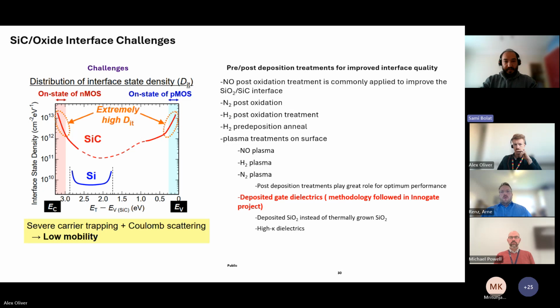If we go to the next slide, I will briefly mention why it is this much worse compared to silicon. So here we see the interface state density distribution across the band gap of our semiconductors. For silicon, we see that the levels are in the order of 10 to the 10. Whereas for silicon carbide, for the as-grown thermal oxide, for the NMOS or for the PMOS, regardless, we have the interface state density in the range of 10 to the 13, meaning that this is a very defective interface, and we have severe carrier trapping as well as Coulomb scattering, and as a result, we end up with an ultra low mobility.